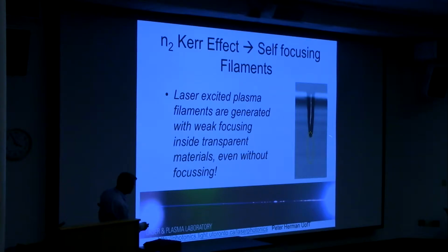I mentioned that the filament that's forming simultaneously with this process is a whole different opportunity. So this is Herman's self-focusing, and basically with a Gaussian-shaped beam, the center of the pulse slows down, and so the wavefront distorts, and then it self-focuses, and when you get to the focus, it stays focused over long distances. And if you get it right, you can see that this white zone shows a positive index change. It's a compressive zone, and it creates stress.